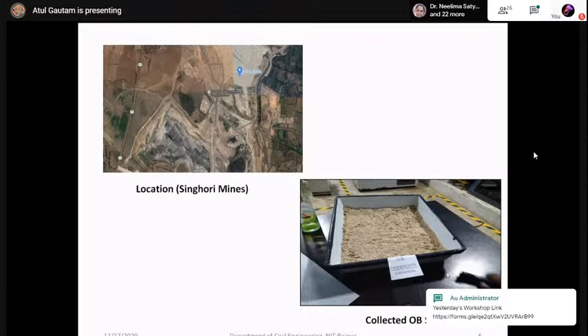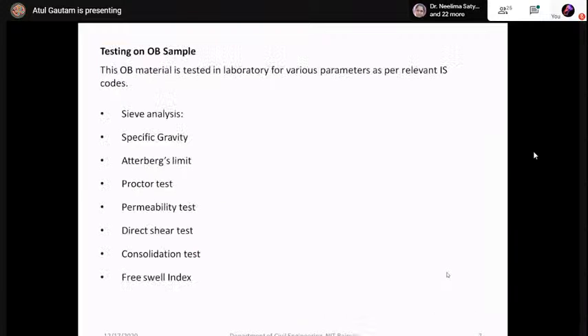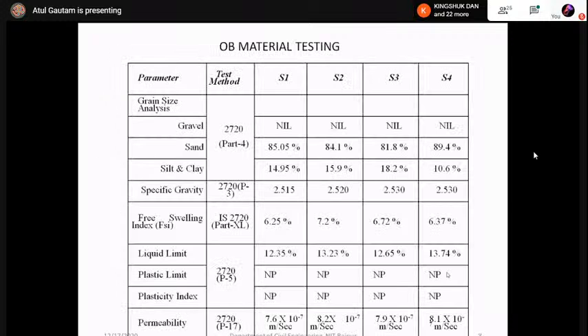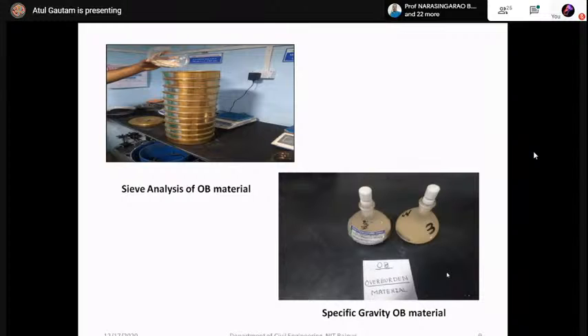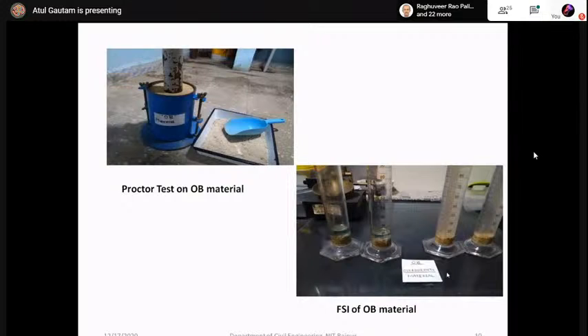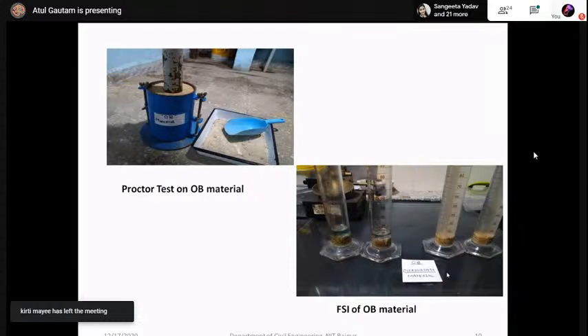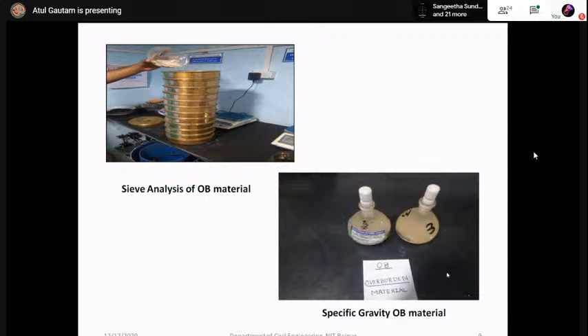This is photograph of the collected OB sample overburden dump. So following tests we have carried out on the OB material: these geotechnical properties, Sieve analysis, specific gravity, Atterberg's limits, Proctor test, permeability, direct shear test, consolidation test, and free swell index. And these are the results. At present, we have selected 4 samples, and these are the geotechnical properties of the material collected from the site. These are the photographs taken during the testing in laboratory. We have conducted Proctor test also to determine the OMC and MDD. We have conducted free swell index test on the OB material. We have determined gravel, sand, silt, clay of this OB, and also specific gravity test.